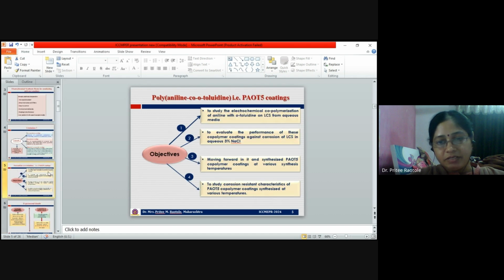The objectives of the present work are to synthesize by electrochemical copolymerization of aniline with o-toluidine on low carbon steel from aqueous media, to evaluate the performance of these copolymer coatings against the corrosion of low carbon steel in aqueous 3% NaCl solution, to synthesize the PaOT5 copolymer coatings at various synthesis temperatures and to study the corrosion resistant characteristics of PaOT5 copolymer coatings synthesized at various temperatures.